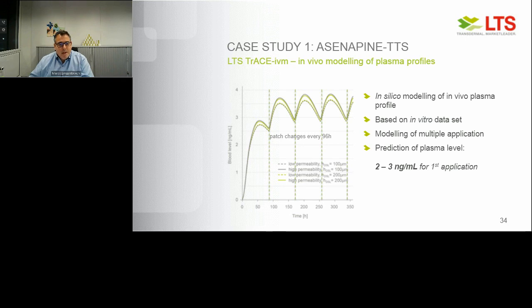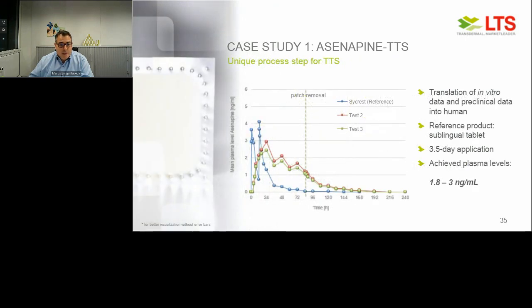And the next step, we actually go to a clinical trial, and we are applying 2 test formulations over 3.5 days. As you can see here, the red and the green curve. And we're measuring the mean plasma profile compared to the reference product, which is a sublingual tablet, which was applied twice within this clinical trial. And we can see here that we achieve plasma levels of the transdermal applications between 1.8 and 3 nanograms per milliliter, which is pretty close to that what we have simulated before for the first application.